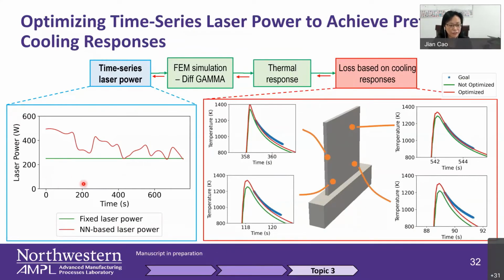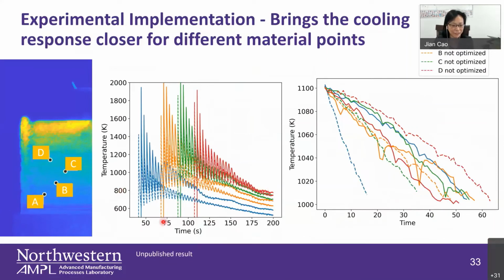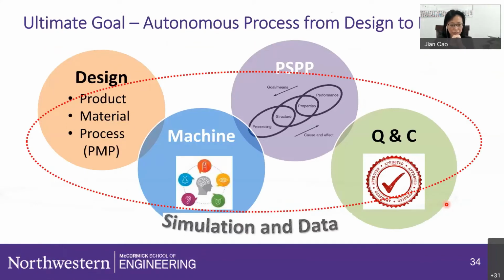And you can see that the laser power has been changed quite interestingly. Then we implemented that in our experiments. Without that, with just constant laser power, the thermal readings, the temperature readings from these dashed lines, are very widespread. And when we implement the laser power from the differentiable simulation, you can see that they are much closer to each other.